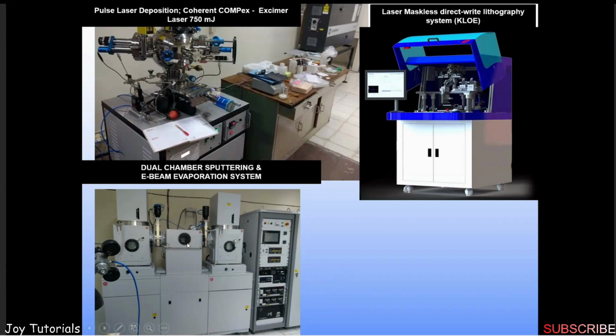Both together for the designing of multi-layer films. One can transfer. This is a transfer arm. One can go from one end to the thin film deposition by the sputtering system. This has 4 heads, 4 sputter guns for different materials. And then one can in situ come back to the E-beam electron beam system. This is the electronic control for this. One can have a multi-layer, so 100 layers, just programming of this structure through the electronics.